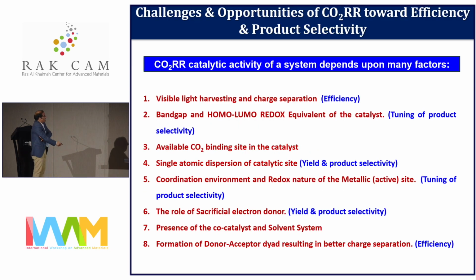Over the years, what we understood is how the catalytic efficiency and the product can change the course of the reaction. Your catalyst should have visible light harvesting properties and should efficiently create charge separation, which can increase the efficiency. The band gap and HOMO-LUMO redox equivalent of the catalyst can tune product selectivity. You need an available CO2 binding site in the catalyst, and a single atom dispersion of the catalytic site over the whole matrix. Coordination environment, the redox nature of the metallic site, the role of sacrificial electron donor, presence of co-catalyst and solvent system, and formation of the donor-acceptor dyad for better charge separation are all important.